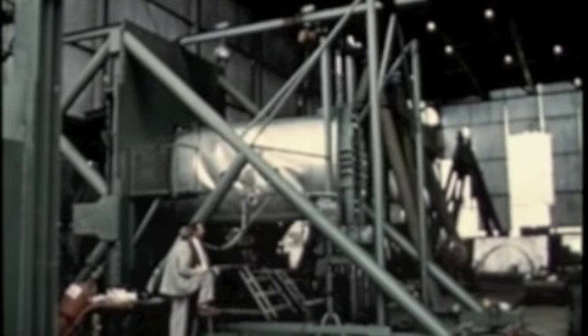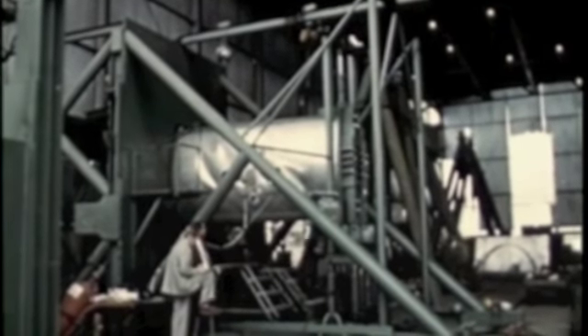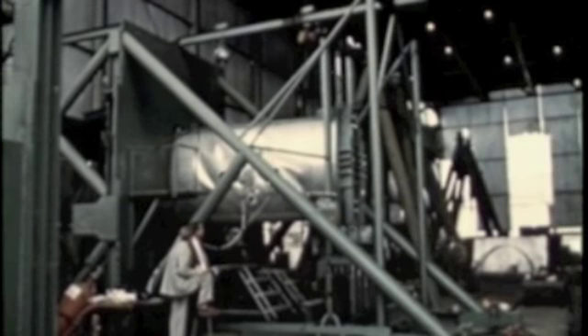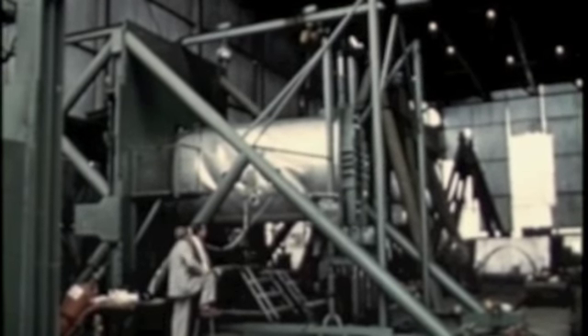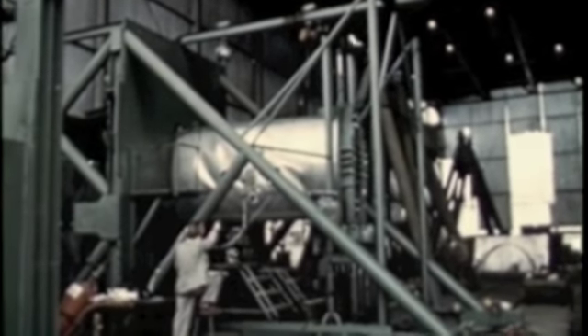A test to measure the shear strength of the fuselage skin is set up. Increased loads are applied to the specimen until stresses far exceeding the effects of the most adverse flight or landing conditions are reached. After loads of 110,000 pounds, the fuselage lost its temporary wrinkling and recovered its normal shape and strength completely when pressure was released.